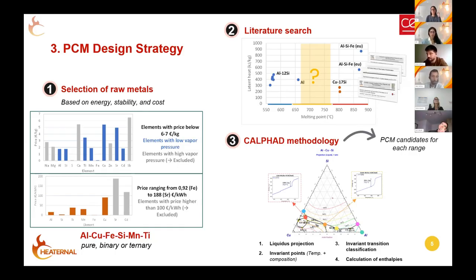In these cases where we need a specific melting point, but there are no available reported options, we use the CALPHAD methodology. CALPHAD allows us to calculate the phase diagrams of these alloys and thermodynamically predict which compositions could be of interest. We focus on those with invariant transformation within the desired temperature range and with expected high transformation enthalpies. By combining both the literature research and CALPHAD methodology, we were able to identify a series of candidates that can cover the 3 targeted temperature ranges.